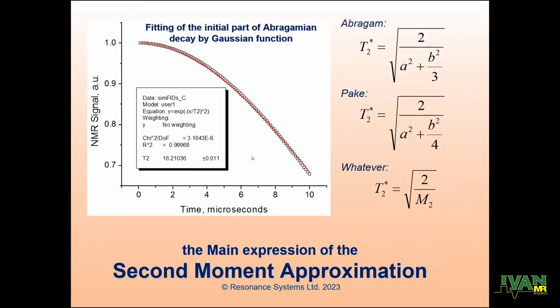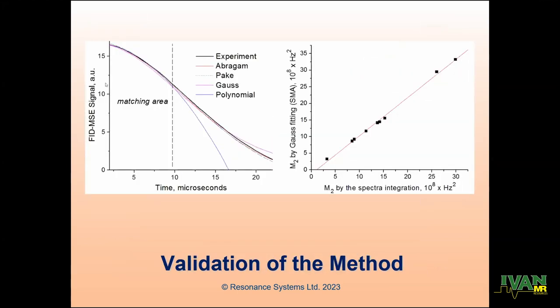So we have developed quite nice approach. We have now applied already the contribution for publication. That's why I'm talking about this quite easily. So, fitting of the different relaxation curves. The black one is the experiment, and the initial 10 microseconds are fitted by Abragam, Pake, Gaussian, and even polynomial function. And they more or less behave equally in the beginning.